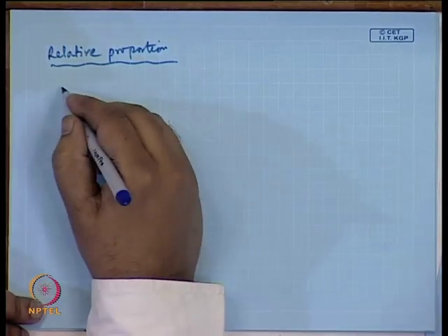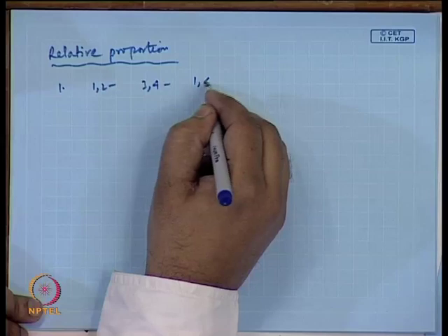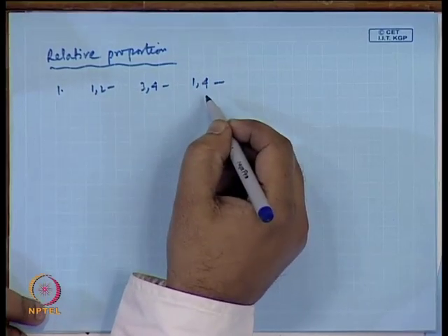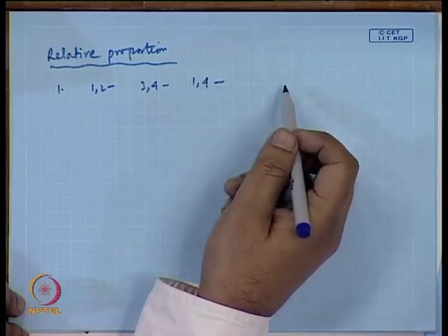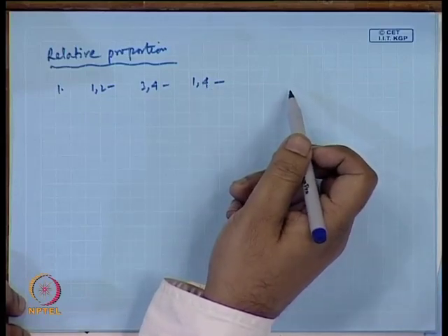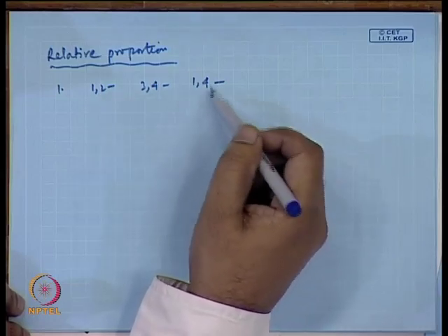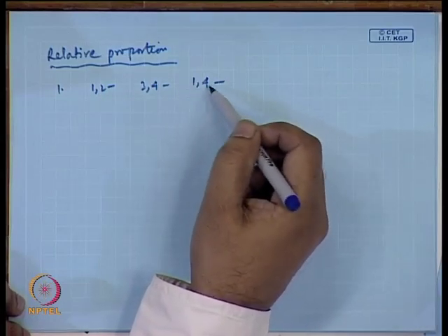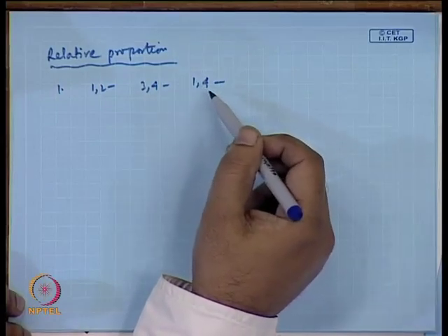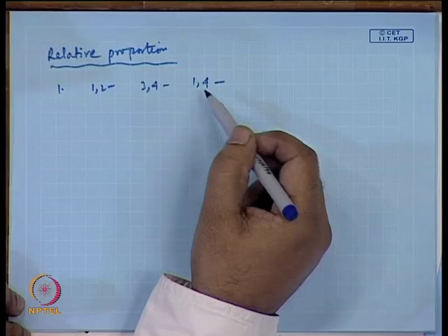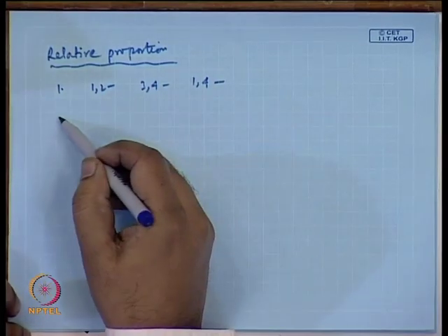Obviously, between these three, it will be the addition which gives the intermediate having the lowest energy that is the predominant product, and in most cases, because the 1,4 addition gives a longer resonance stabilization, this is the preferred propagation mechanism compared to the other two.